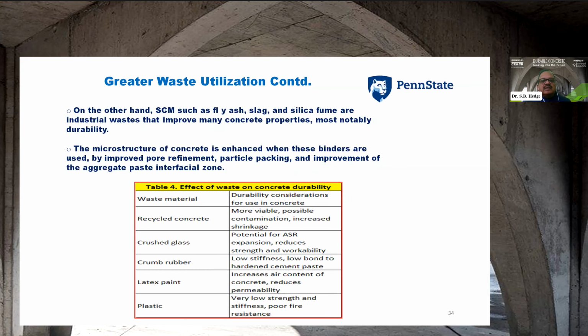And if you see this slide, various waste materials have been used, like recycled concrete, crushed glass, crumb rubber, latex paint, etc. But you can see the effect of that: durability consideration, more voids, possible contamination, increased shrinkage. So the durability may increase or it may hamper also by using this waste material, that we have to keep in mind and make a sort of optimization, what should be the level of addition of these materials, so that the durability should not be hampered. At the same time, these materials are also being used, so we have to have a balance of that.